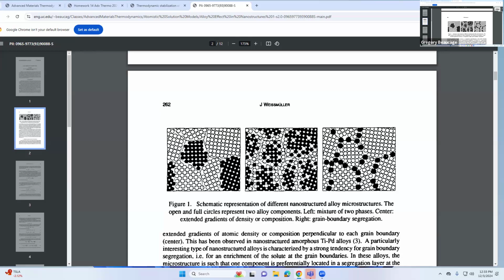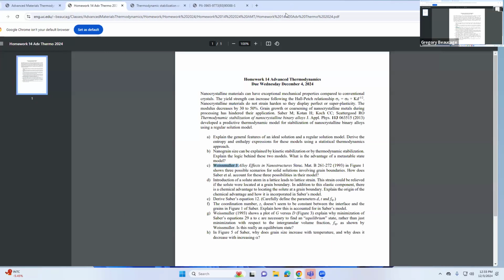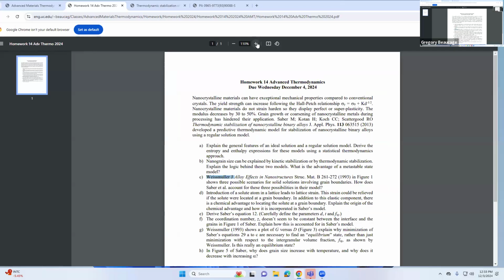domains of black, and then there's a gradient of the white. Or you can have a kind of immiscibility where the black can go to the interface, to the grain boundaries. Then the black can stabilize the grain boundaries. In that case, Weissmuller says there's a thermodynamic driving force for that. And the idea is that people want to get small grains because of this Hall-Petch thing.